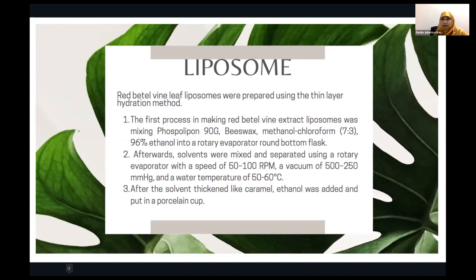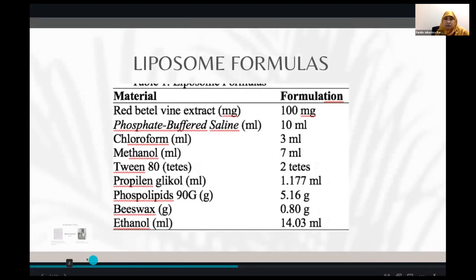After the solvent dries like caramel, ethanol was added and put in porcelain cup. Furthermore, the porcelain cup is heated in water bath. After the ethanol has evaporated, PBS is added. And red betel vine extract, the mixture is stirred with ultrasonic until a cream preparation is formed. The cream that has been formed is then added Tween 80 and propylene glycol. That is liposome formula. The material, there are red betel vine extract, phosphate buffer saline, chloroform, methanol, Tween 80, propylene glycol, phospholipid 90G, beeswax, ethanol.